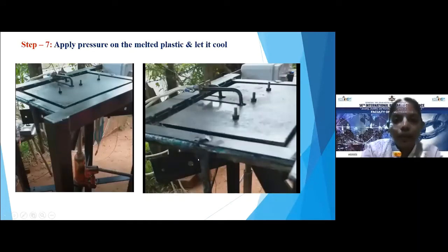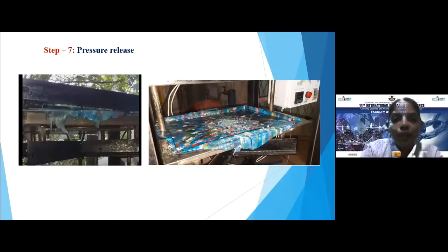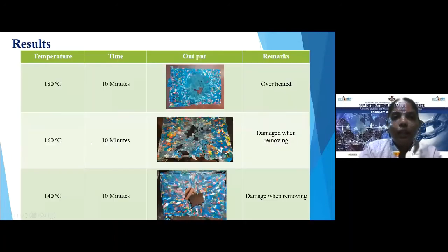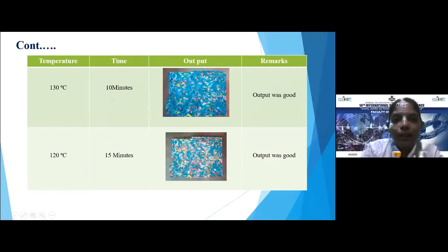Then apply the force on the melted plastic. After 15 minutes, the pressure is released, and the bottom mold moves down. The apparatus was tested by varying the temperature and time. The first output was not good; in the middle, it was broken. But at 130 Celsius for 10 minutes and 120 for 15 minutes, I got a good output.